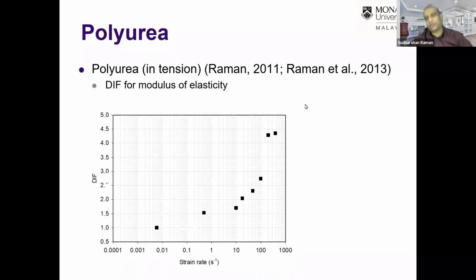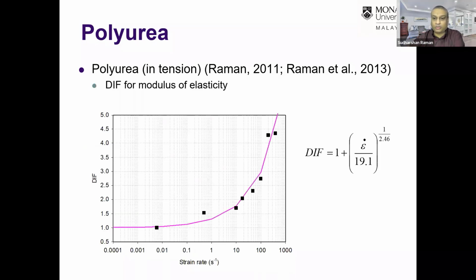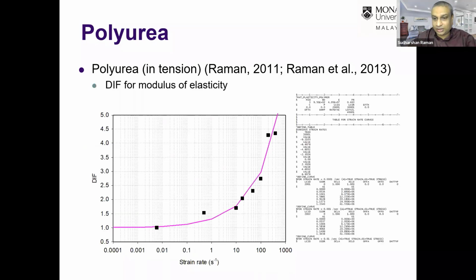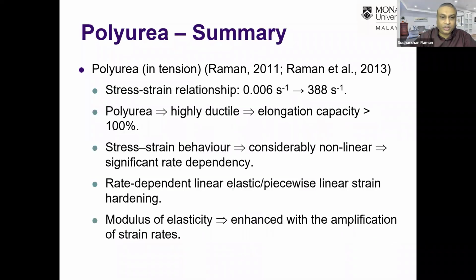So what we did subsequently was to model the dynamic increase factor on different parameters. In this case, for the DIF of modulus of elasticity, we used the Cowper-Symonds correlation, and then we developed a material card to be used in LS-DYNA for the numerical work. What we have used here is material plasticity polymer, or MAT 89.